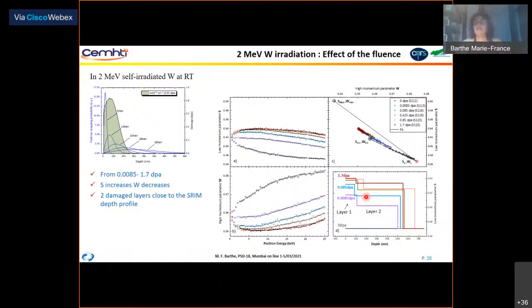That means the thickness of the second layer could be lower, and yes, it could be higher. To our mind, we simplified this damage profile. It's why we have a thickness of the second layer which is larger than what is expected with SRIM. And of course, we also have to think that the SRIM calculations are not so exact. It is a way to get an idea of this profile, but it is not so sure that it stops at 300 nanometers in the case of tungsten ions. Okay, thank you. I hope it was clear for Amarendra.